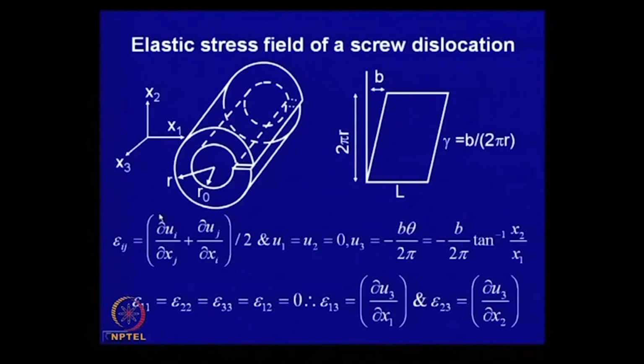In earlier classes we have seen the physicist's definition of strain. We made a distinction between pure shear and simple shear. Simple shear is the one which is the slip process, and pure shear is the strain which represents shape change. So, if you add a rotation component to the pure shear, then you get a simple shear which represents the process of slip.